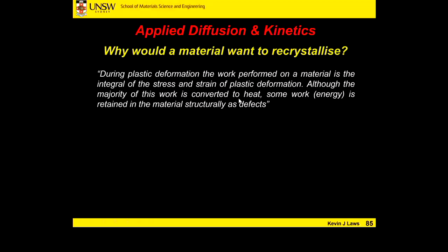So most of that energy is converted to heat, but some work or energy is retained in the material structurally as defects. By deforming the material, our crystal structure that might have been perfect, we're stretching it, we're bashing it, we're putting defects into it. Vacancies, dislocations, we're refining the grain structure, grains become smaller because we're breaking them apart.